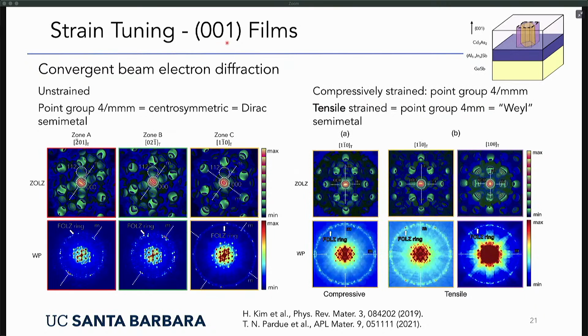So now let's turn to the 001 film. In this case, the fourfold symmetry axis is normal to the film plane. So if you apply tensile or compressive stresses in the plane, you wouldn't expect to lose the fourfold symmetry axis, and indeed, we do not lose it, from analyzing these patterns here. And a compressively strained film is, as expected, in the same point group as an unstrained film, 4/mmm.